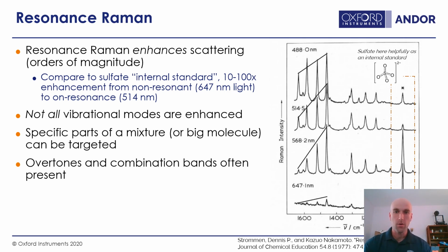So one of the interesting things as well is that if you have a complex mixture, with multiple components, and you have some separation between their absorption spectra, then you can target specific parts of a mixture, or even more interestingly, different chromophores on the same molecule. What I mean by targeting is that you will be on resonance with one component or another. You'll get the enhancement in the component that you're on resonance with, and you won't on the other components.